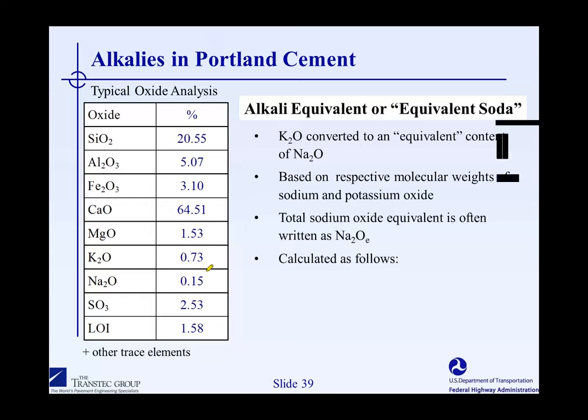We're dealing with two types of alkali important in cement. We have our potassium, we have our sodium, and we like to try and use a single number to describe the alkali content. It's easier to deal with one number than two. So what we do is we convert the potassium oxide to an equivalent content of sodium oxide. And we do that by using the respective molecular weights of the two compounds. We combine those and we call the combination the total sodium oxide equivalent, often written as Na2OE, the E being for equivalent. Sometimes you'll write Na2OEQ instead, the EQ being for equivalent. And the sodium oxide equivalent is calculated by,